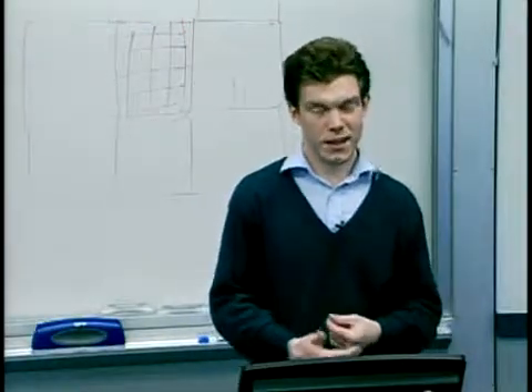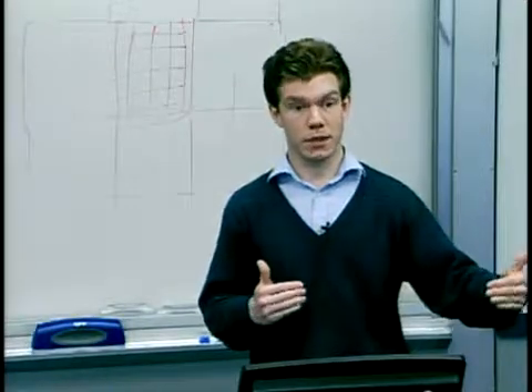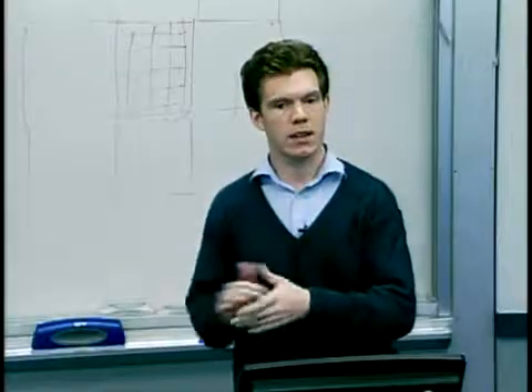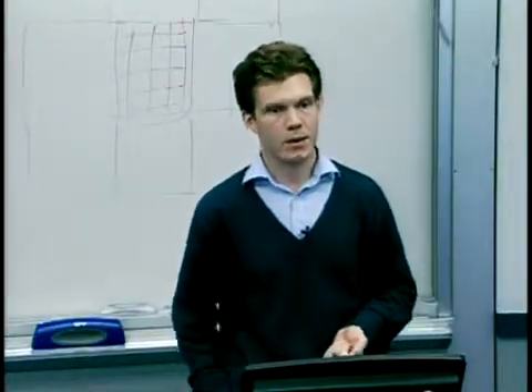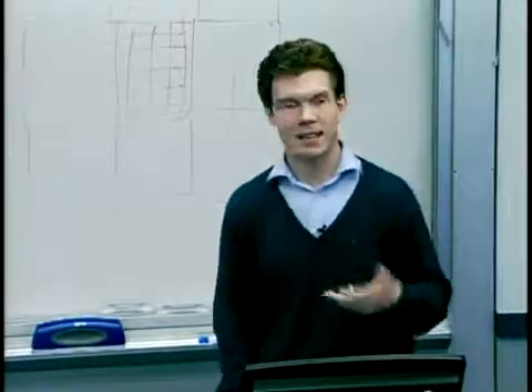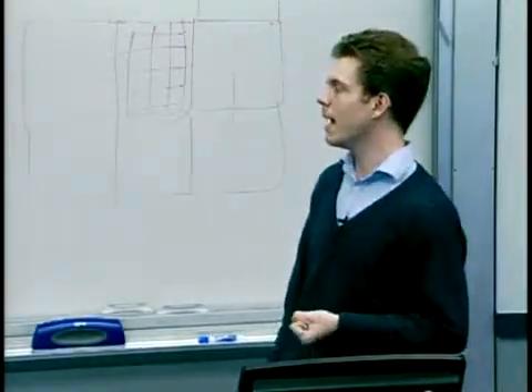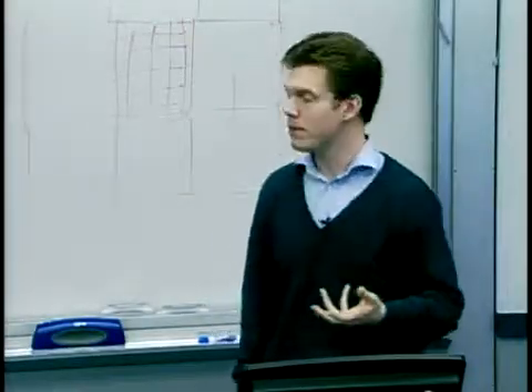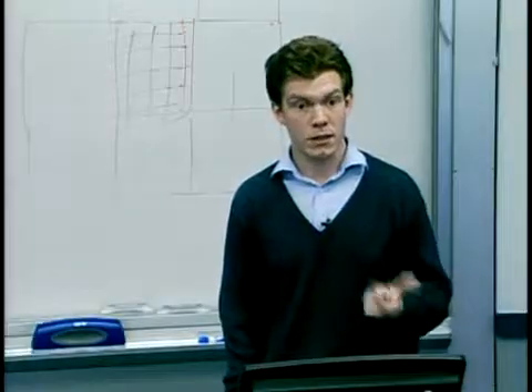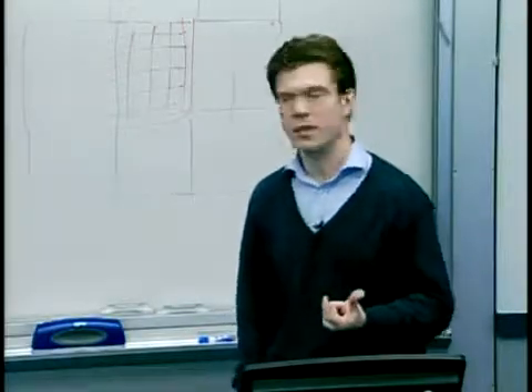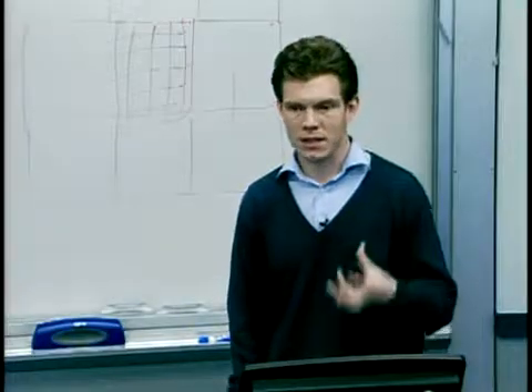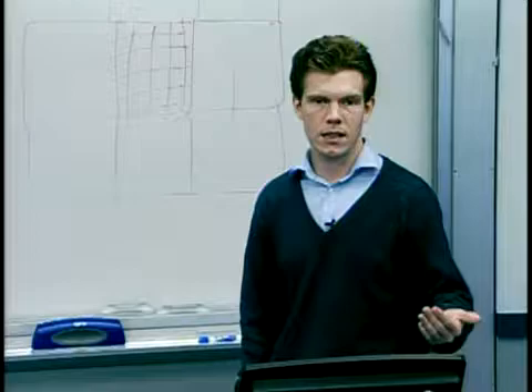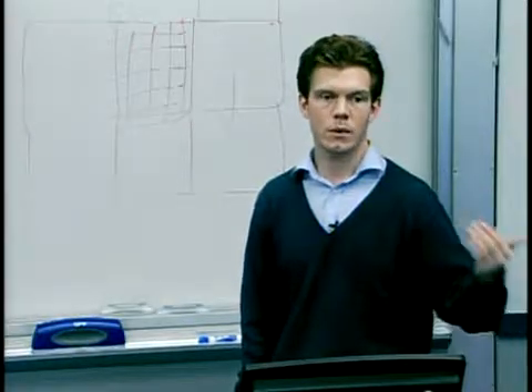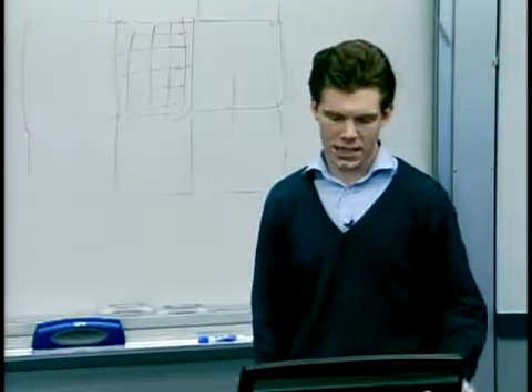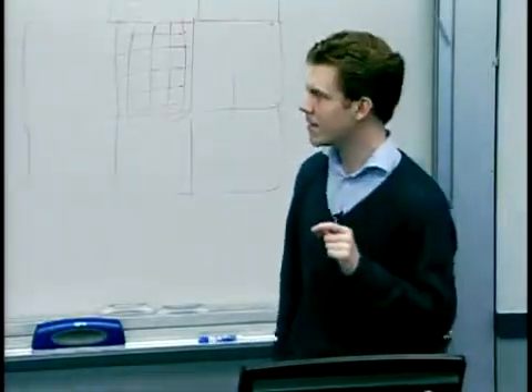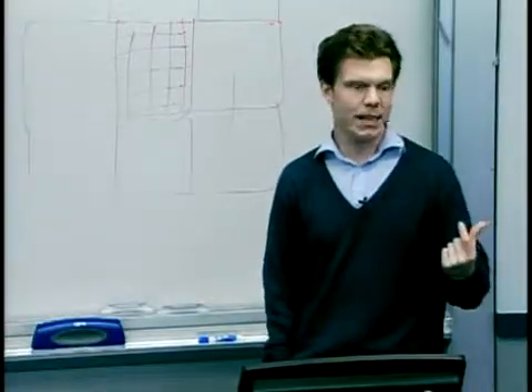Now, question is, can we adapt our simple model to capture this viscoelastic behavior without increasing the computational burden very much? And well, the next thing you might think of doing is adding a linear dashpot into the system, and maybe it's linear. That would be the first thing to try. Maybe you do need to capture the idea of a yield stress as well, and maybe you need to capture the idea of a strain rate dependence, which in PMMA is such that the yield stress increases substantially with strain rates above about 10 to the minus 2 per second. So in fact, we just tried adding in a linear dashpot.